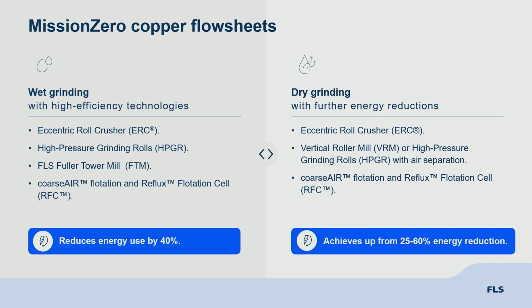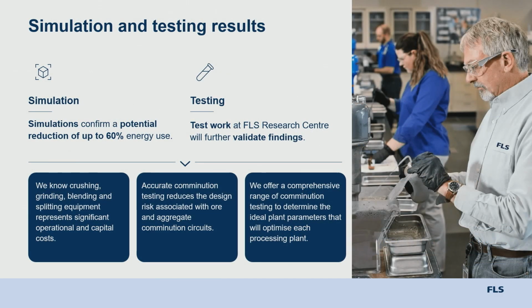So one of the kind miners in America gave us 30 tons of very hard, competent ore, very low grade, and we used that. We collected a representative sample, took it to a facility to cone and quarter, dried it, and shipped it to our R&D department in Salt Lake City here. We're out at Midvale. We have a large technology center out there. So we started looking at the simulations. We got the material in, and we pre-crushed it. We did metallurgical work on it, liberation work, to see what the grind size should be. And then we also did the pre-grinding.